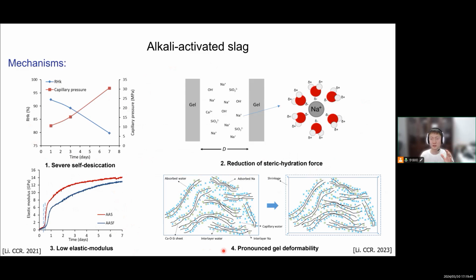So when there is a constant pressure, even if the capillary pressure doesn't increase anymore with time, the constant pressure can still cause the gel to shrink because there is a certain creep. It is actually even larger than what we observe in Portland cement.